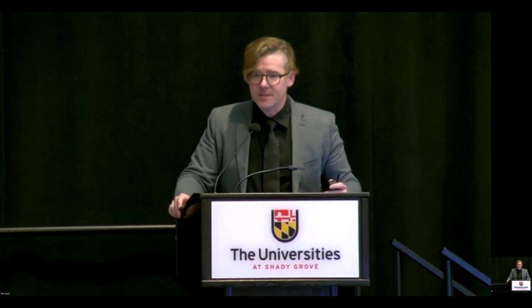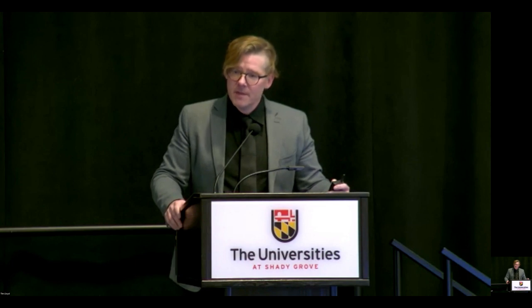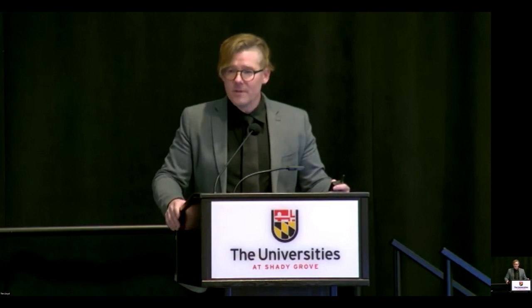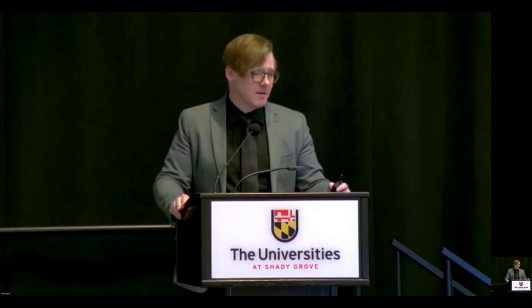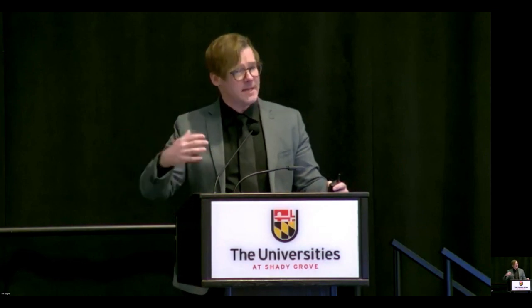This would have a randomizing effect on the repeat unit blockiness. This is an inherently non-deterministic system. It's an unconventional chemical system. And we can understand why first by just looking at the forward propagation and depropagation and how this affects how we might model this to gain an understanding. It turns out that because of that reversibility, you actually have to calculate the concentration of every possible sequence, which for, let's say, a polymer with a degree of polymerization of 100, and you have two choices, you'd need on order of 2 to the power of 100 equations in order to model this system deterministically. That's like 10 to the power of 30 in base 10. It's a number that is so large, it just is meaningless. It's essentially infinite. So you can't write down a deterministic model for this. Now, there are good reasons why we need a deterministic model, though, so we can fit a model to data, extract parameters, and then derive molecular meaning and say, this is what the sequence of this polymer looks like.